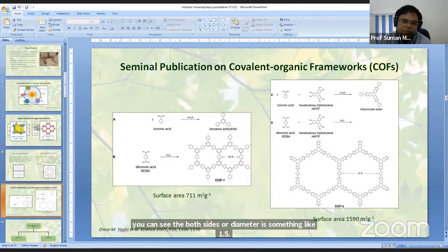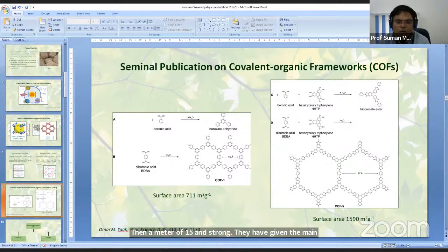They gave the name of this compound COF-1, or covalent organic framework 1. And they found that the surface area of this particular porous material is about 700 square meters per gram. When they used the same diboronic acid to react with hexahydroxytriphenylene and did a dehydration reaction, they got bigger pores with a pore diameter of about 27 angstrom, 2.7 nanometer. They named it COF-5, and the surface area is about 1590 square meters per gram, which is quite high in nature. They published this work in the world famous journal Science in 2005, and there starts the beginning of the covalent organic framework.